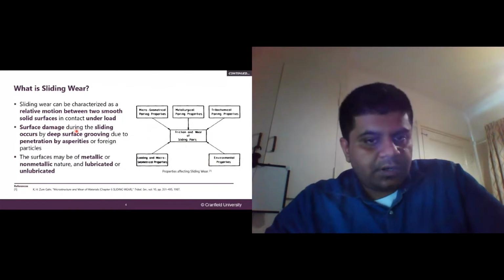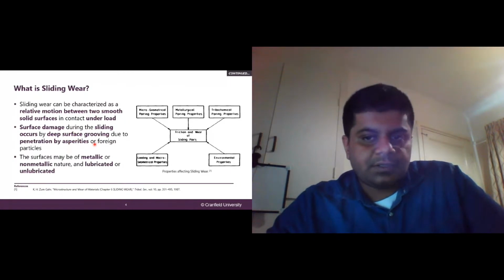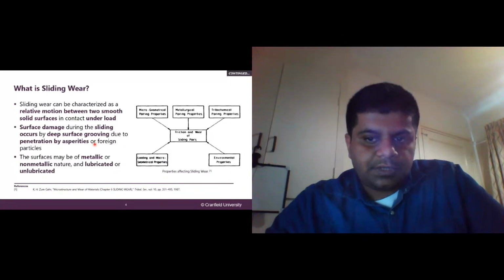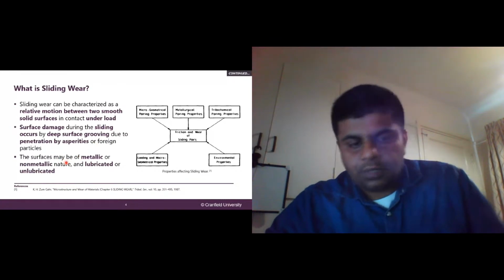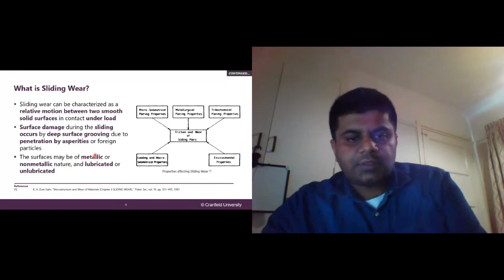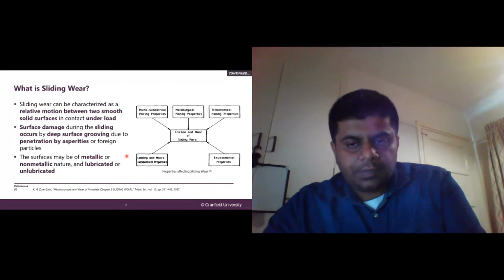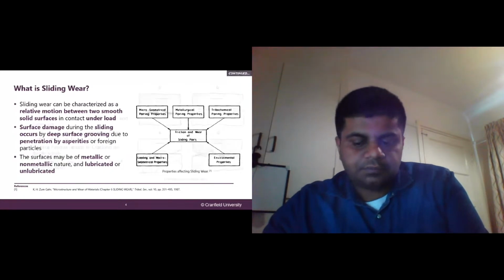The surface damage that occurs during sliding is by deep surface grooving due to penetration of asperities or foreign particles. That is under investigation here, but we're only looking at the macro level friction and wear. We're not really considering the asperity or micro level work here. So we would just be talking about the penetration depth and how it changed over time. The surfaces may be metallic or non-metallic, which does not really make a difference, because as long as you choose the right ball and surface combination, you'll still be able to end up with good wear combinations.